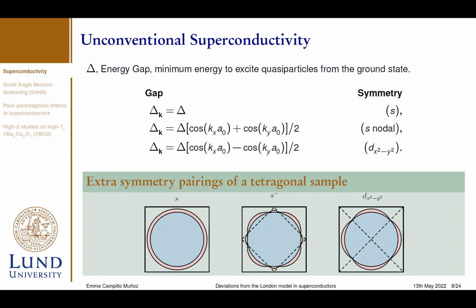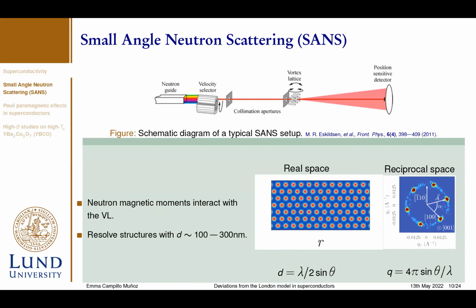Right, so now the question that comes up is, how do we study these materials? As Sebastian explained before, when we are working on monochromatic neutron experiments, or in our case, monochromatic small angle neutron scattering instruments, we usually have a neutron beam with several energies or wavelengths. Then we have a velocity selector, and we choose a particular wavelength that we are interested in. After passing through collimators, the beam will interact with the vortex line lattice of our sample. I will remind you that the sample has already been cooled down below the critical temperature, and we also apply a certain magnetic field to have the superconducting phase in the material.